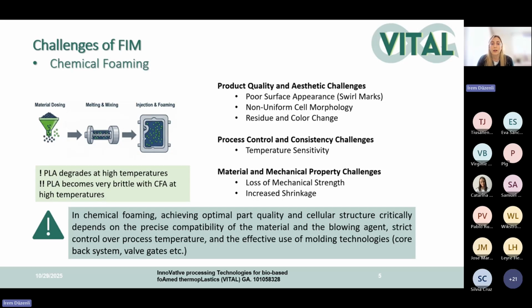Our other challenges are process control and consistency, especially with PLA material. In this project, we see some problems about the process conditions. We really need to optimize them, especially the temperatures, because PLA degrades at high temperature. Even when we use chemical foaming agents, it starts to degrade at an even lower temperature, and our parts can become very brittle after adding the chemical foaming agent. These are very important points for the process.